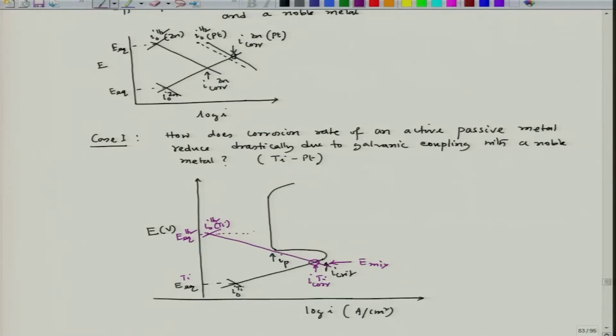Now, the point which is the hydrogen evolution reaction point is the E equilibrium. This is the point, and this is I0 hydrogen on platinum surface, provided the platinum is there on top of titanium surface. That means if we have a titanium piece with kind of dots of platinum on top of it, and this is the titanium piece.